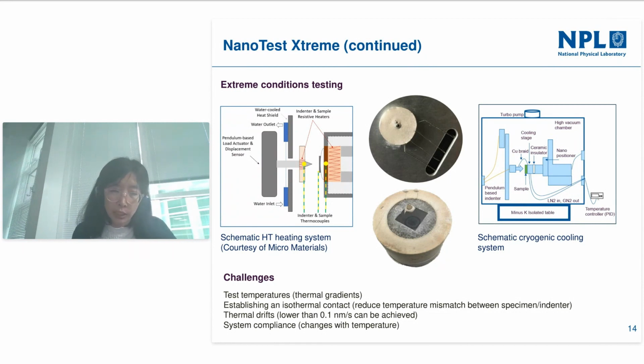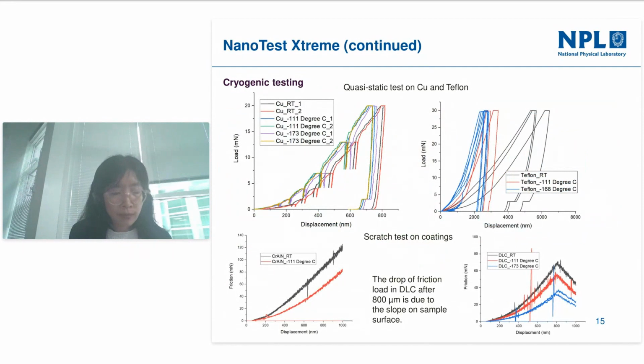High temperature testing has a few decades of research, and to improve the thermal drift and also to calibrate the compliance of the system, the cryogenic test has recently attracted attention due to the drive of the hydrogen economy. So instead of high temperature results, here are some preliminary results from cryogenic tests. The test results are on polycrystalline copper and also on the polymer Teflon,